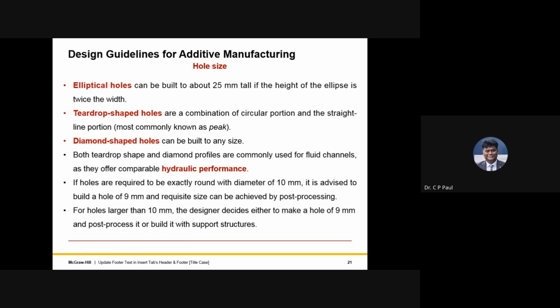Now, as I already told you, ellipticals can be built about 25 millimeter tall if the height of the ellipse is twice the width, and the same for teardrop shape holes, a combination of circular portions and straight line portions as a peak. Teardrop and the diamond profile are commonly used in the fluid channel as they have comparable hydraulic performance. You must be knowing when you do the fluid dynamic design, you use hydraulic diameter to identify some of the things. And here is the same.